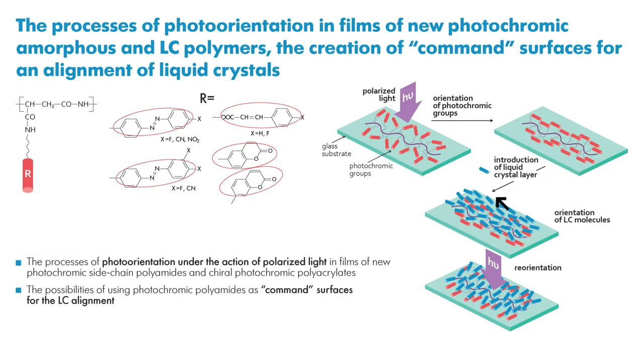If a layer of liquid crystal is applied over such film, then liquid crystalline molecules will be aligned along the direction of orientation of the photochromic groups. In other words, polyamide acts as a command surface that controls the orientation of the liquid crystal. Moreover, by changing the direction of polarization of light, one can also control the direction of orientation of liquid crystalline molecules.